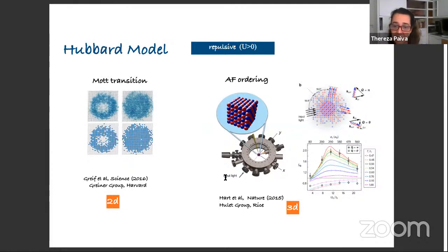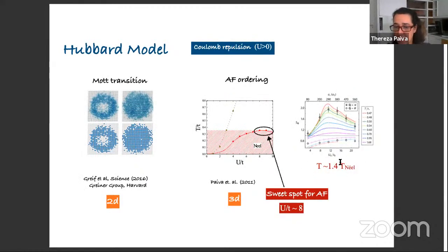And as for antiferromagnetism, it's harder to see because the ordering temperature is lower. And also because we do need to be in 3D to see long-range order in the Hubbard model, and I'll come to it in a moment. But this experiment from Hulet's group at Rice is a very nice experiment where he has done spin-sensitive light scattering. And so what he did observe here is actually the spin structure factor, and it has a maximum here. The temperature where this experiment is done is still above the Néel temperature.